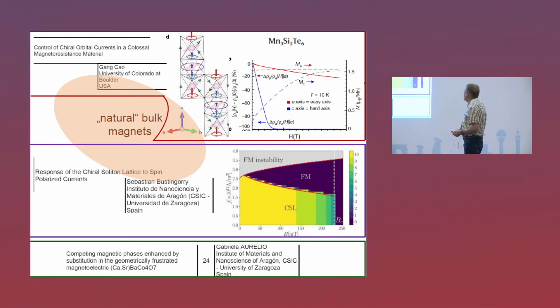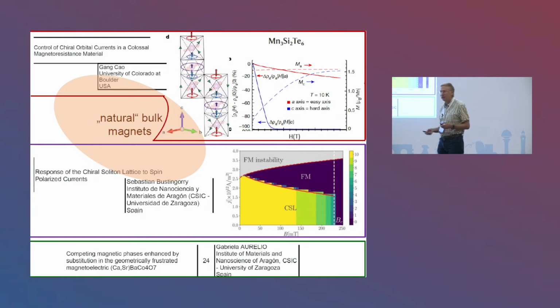A more or less related theoretical work on the chirality problem, on the chiral soliton lattice, was discussed in the talk presented by Bustingorry from Spain, where a phase diagram was proposed in which the chiral spin lattice could be controlled either by magnetic field or by applied current. It was predicted that this chiral spin lattice has a certain phase stability area, but it could be turned to the fully forced ferromagnetic state either by application of a stronger current or a stronger magnetic field beyond the critical value. But surprisingly, when the current is increased further, the ferromagnetic order is surprisingly destroyed.